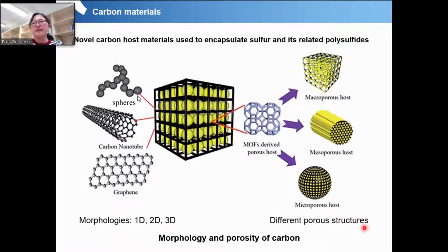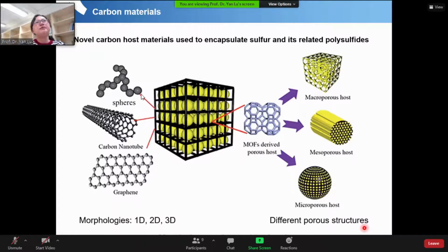And in that case, they could see it can work efficiently for lithium sulfur batteries. Actually, before her, people also thought about the concept of lithium sulfur due to the extremely high theoretical capacity value. Unfortunately, the system did not work very efficiently because you need a sulfur host material, and sulfur is insulating. How can you homogeneously embed your sulfur into your host?